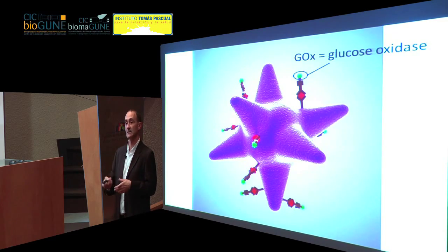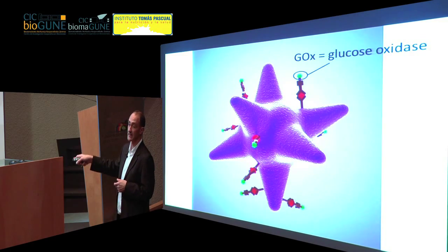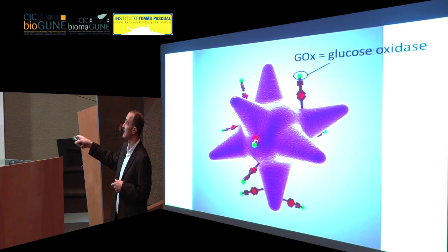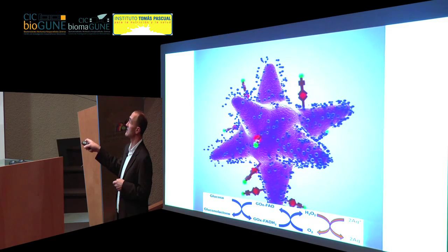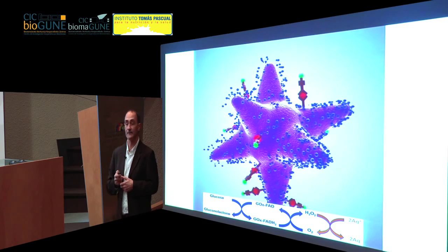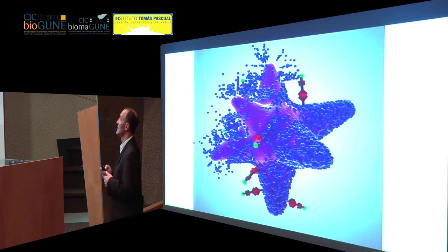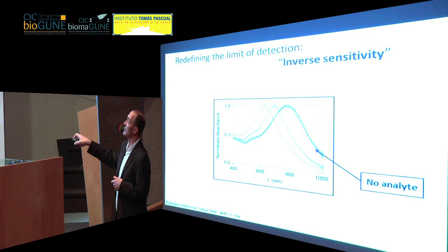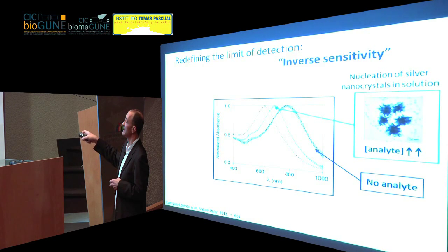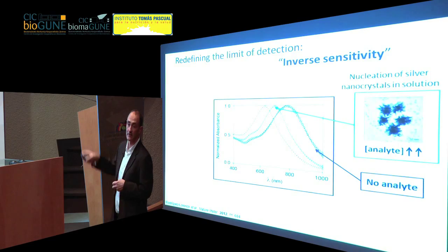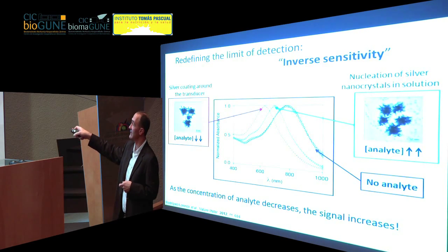And then in the presence of silver ions, if this reaction happens, the glucose oxidase should be here on the surface of the particles. Then the combination of the glucose oxidase with the catalysis from the nanostar would lead to the reduction of silver and deposition on the surface of the metallic particles, like this. So what we find is that indeed, when we do the experiment with no analyte, nothing changes. If we do it for a high concentration of PSA, we get some shift of the plasmon resonance band. But if we do it for a much lower concentration, we get a further shift.